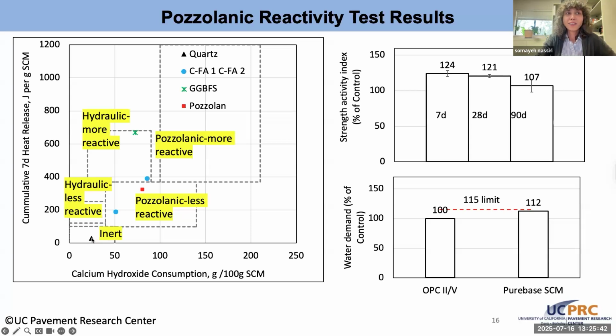This box down here is our reference for an inert material, which is just the ground up quartz. These are the materials that are not pozzolanic and would not yield any of those additional benefits that we get from pozzolans, like additional calcium silica hydrate or calcium silica aluminate hydrate, and all of those things that add durability to the concrete.